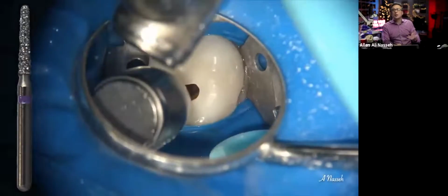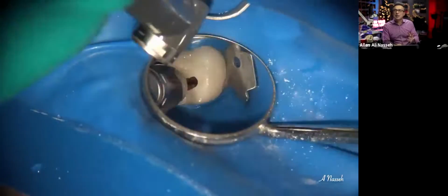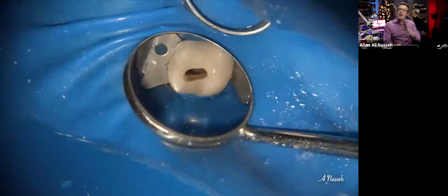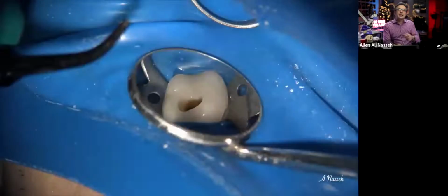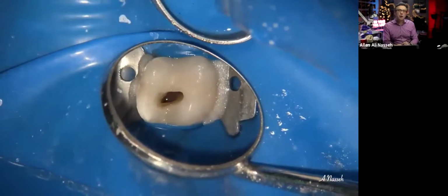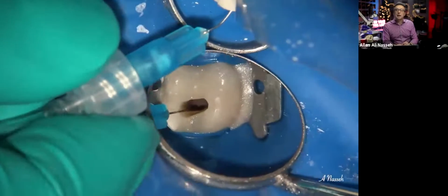So in this particular case, we go in and make an access preparation through this zirconia crown that he had, or lithium disilicate, actually I don't remember right now. But either way, we make an opening in there on top, and just use this blend protocol that I use. We've helped develop it with the idea of austenitic and martensitic files, and this 3D file to go in and clean that area of internal resorption, and get all of the canals, the MB1 and MB2 were joining together, to a size 40-04 EndoSequence, and do our irrigation and disinfection. I'm using negative pressure at the very end.